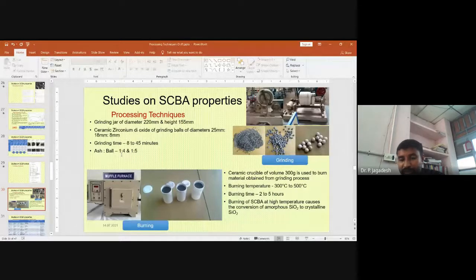It will take 4 months since I can get only 1 kg of cement per 2 days, or per kg for 1 day. If I go for this burning temperature, it should be cooled. If kept at 500 degrees Celsius, it should be cooled for minimum 3 hours so we can handle the ceramic crucible, or else you could not even touch those things. I had worked for a minimum of 4 months to prepare almost 50 kg of cement. Kindly remember the time taken for this thing.